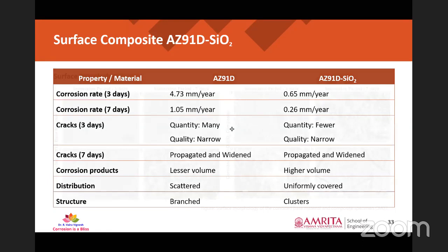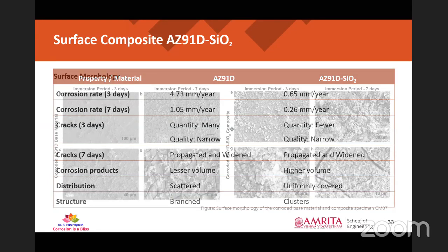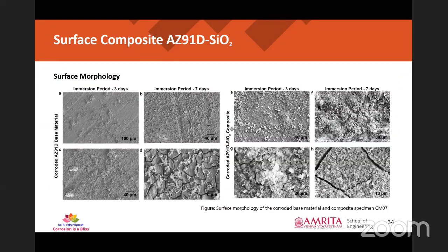So we can compare the surface morphology of the corroded base material and composite specimen over here. The immersion period of 3 days and immersion period of 7 days are given for reference. We could literally see that after 7 days of immersion, the composite specimen has a uniform spread of corrosion products over the entire surface. Whereas in the case of the normal base material, that is AZ91D, we had only limited dispersion of corrosion products too. So that is why we had a high corrosion rate in this case of the magnesium alloy.